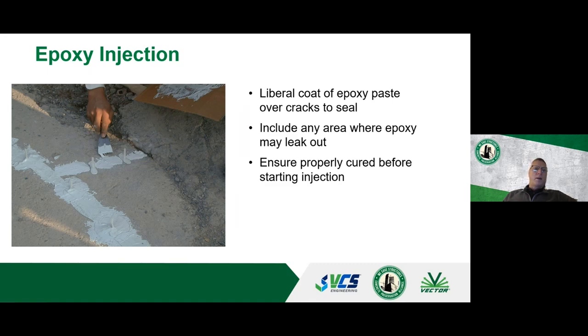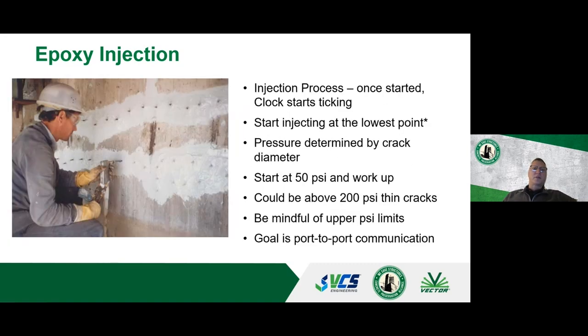80% of the time when I see failures in epoxy injection, it's because you don't allow this to cure. And they make the epoxy paste in many different forms and fashions. So you pick the one that's suitable for you, let it cure up, and then do the injection.